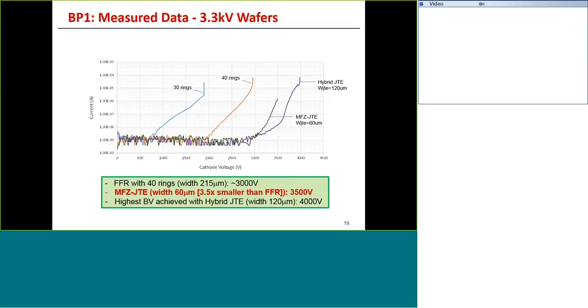In addition, we have a termination we call the hybrid JTE. This is slightly wider than the MFZJTE, but shorter than the 40 ring termination. And this is an excellent termination that gives us breakdown voltages as high as 4,000 volts.